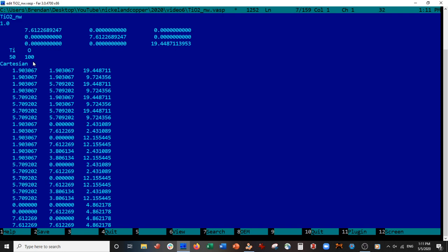Okay. And this is really nice because you can clearly see that the TiO2 stoichiometry was preserved. Usually, my experience is when you make these nanostructures, you sometimes don't exactly preserve the stoichiometry. It's well known in scientific literature that you can have astoichiometric nanostructures. You might have titanium-rich, oxygen-rich, or if you're using cadmium selenide, you might have selenium-rich, cadmium-rich. This is very common. But in this case, it works out very nice.